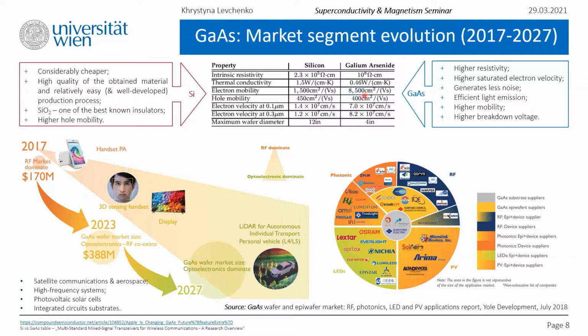The second disadvantage of gallium arsenide is no oxide. So you have to perform a chemical vapor deposition to get an oxide or some nitride insulating layer on it. And even then it would have worse quality and won't stick nearly as well as the natural oxide of silicon. SiO2 is one of the best known insulators. So in other words, gallium arsenide makes very bad MOSFET transistors.